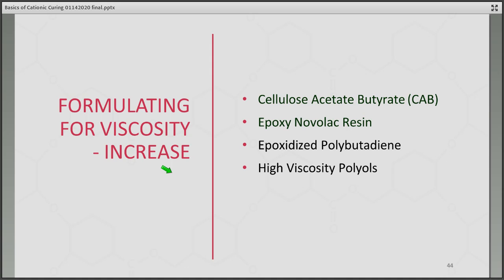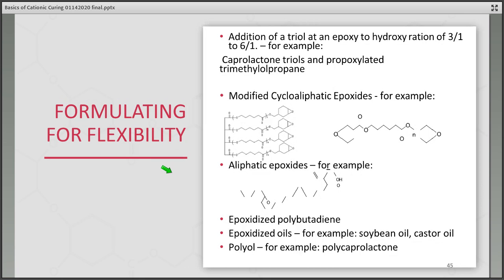Okay, what if you wanted to go in the opposite direction? Instead of reducing viscosity, you needed a higher viscosity in your formulation. For example, if you're applying it to a vertical surface or a surface that's on an angle, and you don't want it to start to creep before it fully cures. In this case, you could blend in a cellulose acetate butyrate or CAB material to increase your viscosity, perhaps use an epoxy Novolac resin or epoxidized polybutadiene, or perhaps a high viscosity polyol. So all these are good ways of adding to your formulation to increase the viscosity, yet still get a good curing material.